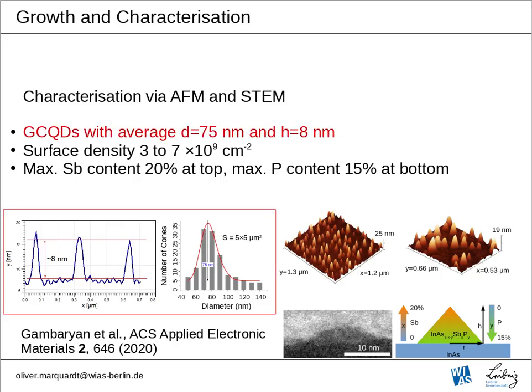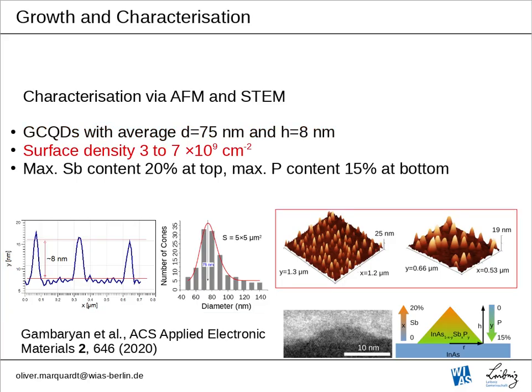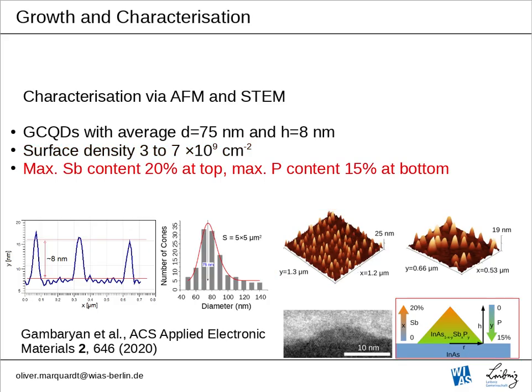We have seen first of all that our graded composition quantum dots exhibit an average diameter of 75 nanometers and an average height of 8 nanometers. The surface density was estimated to be 3 to 7 times 10 to the 9 per square centimeter. It would be typical for LPE grown systems to see the maximum of the antimony content at the top of the systems, which we estimate from strain profiles and composition of the initial liquid to be about 20%, and the maximum phosphorus content of 15% at the bottom of the system. Both decrease to zero, for the antimony content at the bottom of the system and for the phosphorus content at the top. We assume that our graded composition quantum dots have a conical or lens shape. We are not completely sure about that.